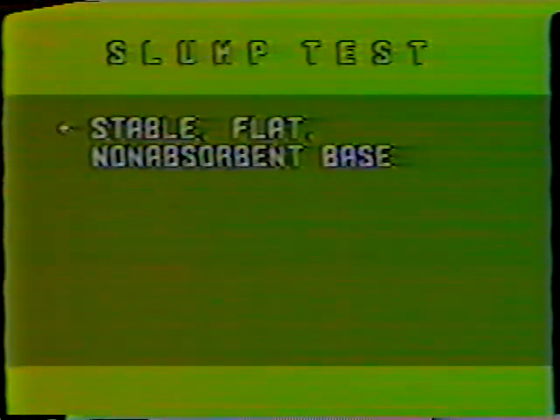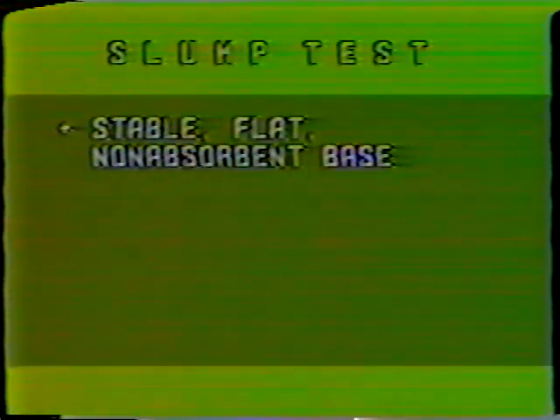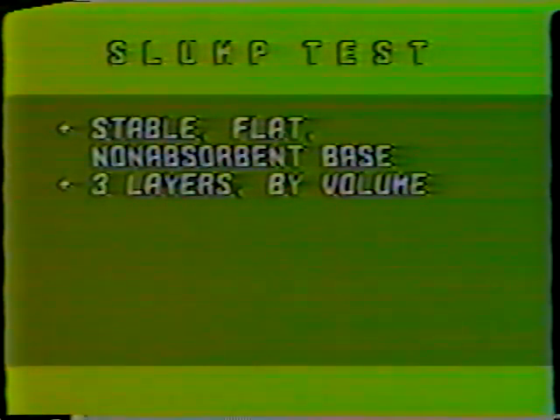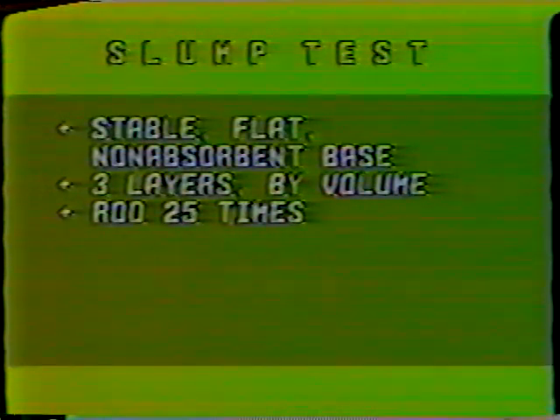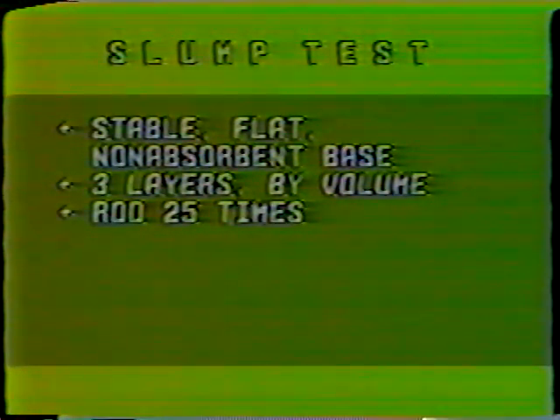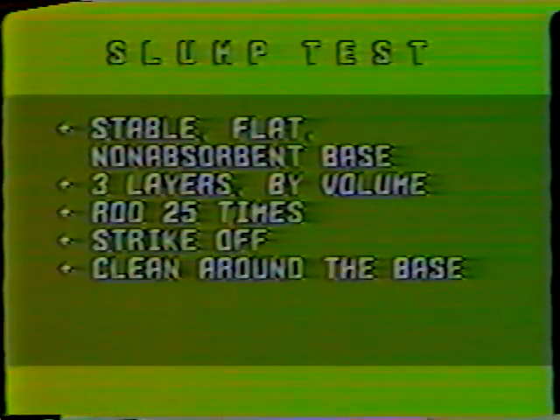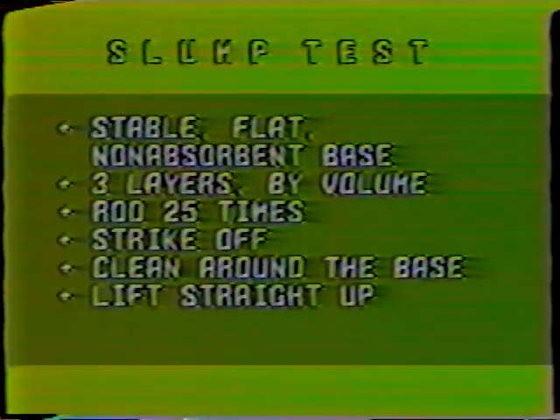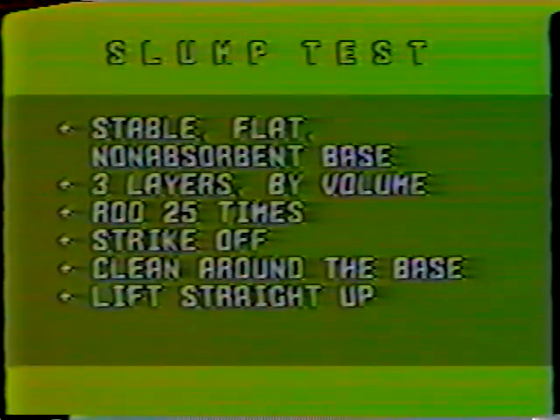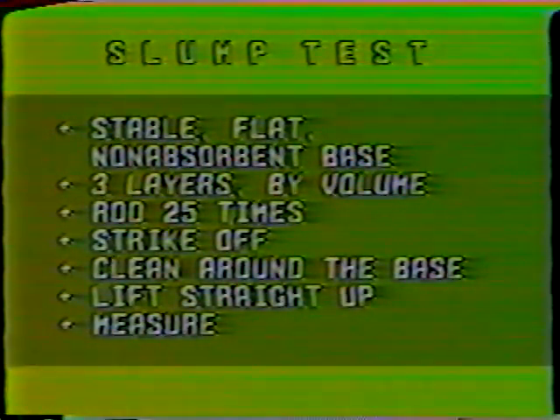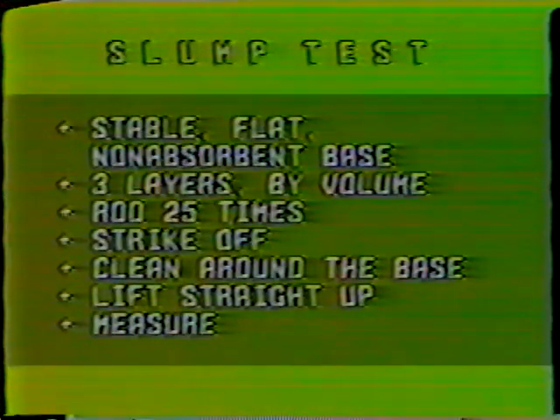And that's the slump test. On a stable, flat, non-absorbent base, fill the cone in 3 layers by volume, not by height. Rod each layer 25 times, spiraling toward the center. Strike off the top layer. Clean around the base of the cone. Lift the cone straight up without twisting or tilting it, and measure from the bottom of the rod to the center of the top of the concrete. There's a time limit too. 2.5 minutes between the point where you start filling the cone to when you measure the slump.